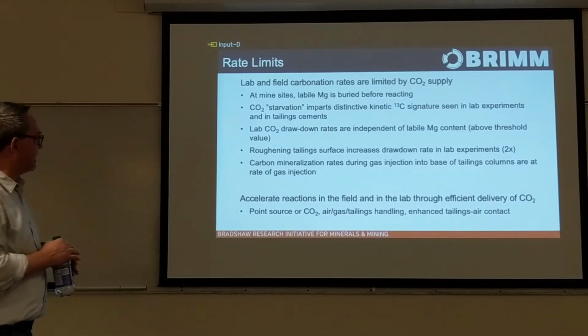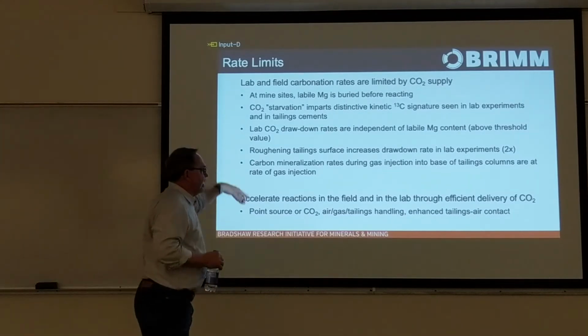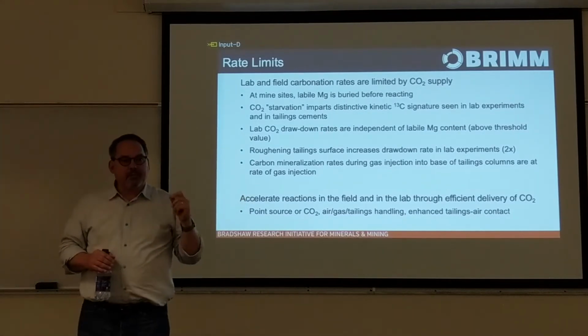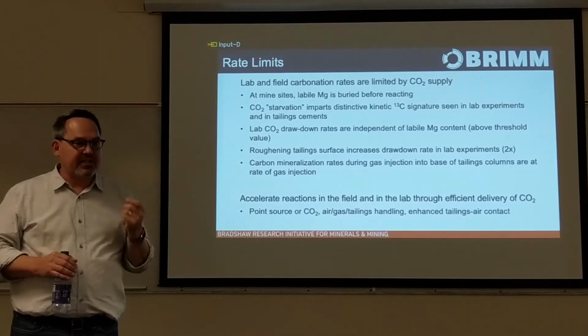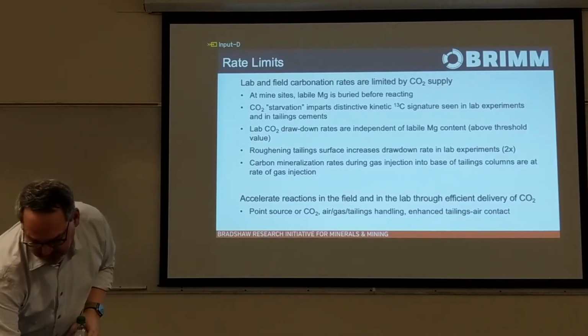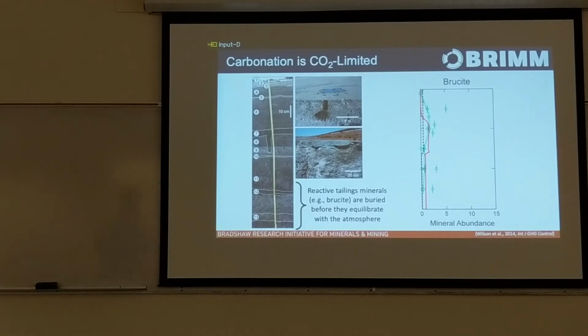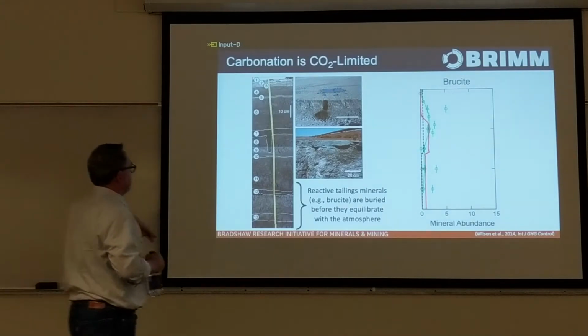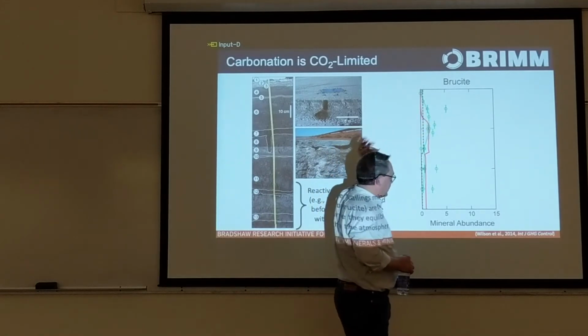So I'll show you a little bit of evidence for these limits, and then talk about how we optimize our process to treat the most reactive tailings. So this is an example from the Mount Keith nickel mine. We can trench down into the tailings, and in this case one of the reactive minerals is brucite, which is magnesium hydroxide.